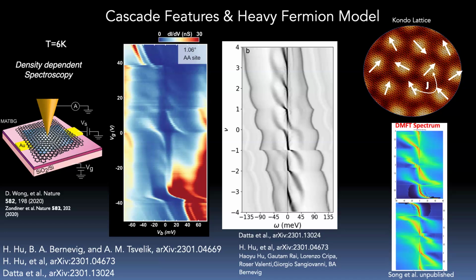They also recover some of the features that we see in the data, and in particular, what this field has focused on is this cascade of transitions that happen before filling. It looks like the system resets itself every quarter filling, so there might be some quantum physics even at very high temperatures, and this requires further experiments to really prove. But I wanted to show this as essentially showing that the normal state is for sure strongly correlated. There might be some quantum physics in the normal state, but there's local physics of electrons living on this AA site and talking to each other through conduction electrons.